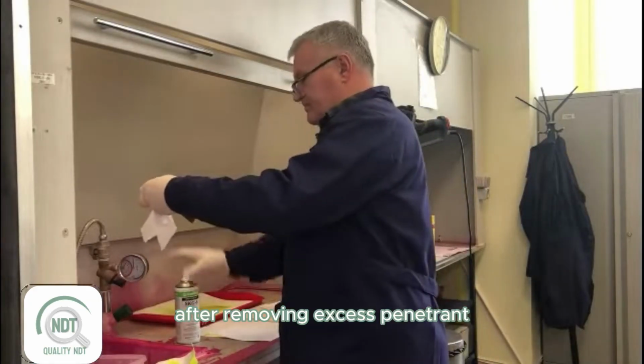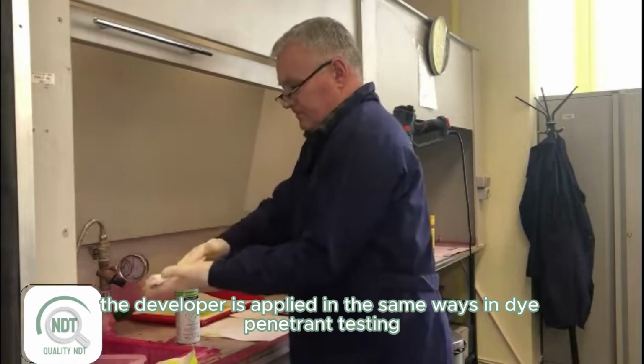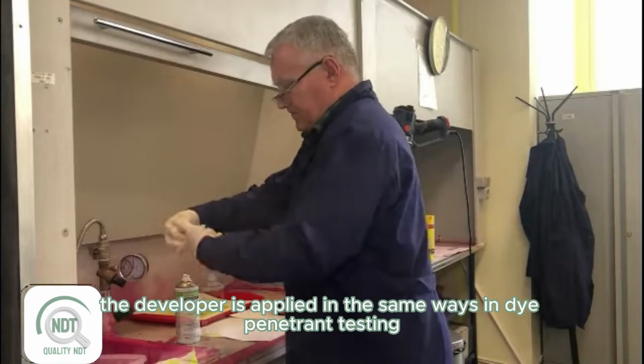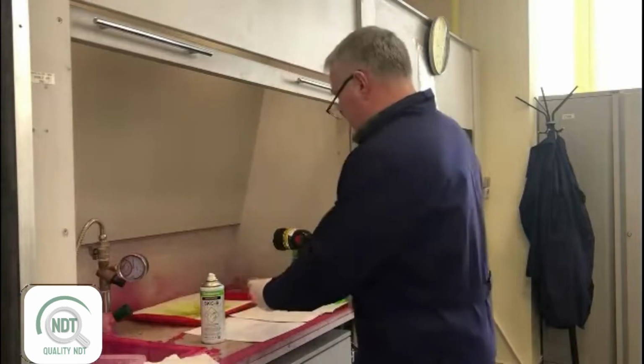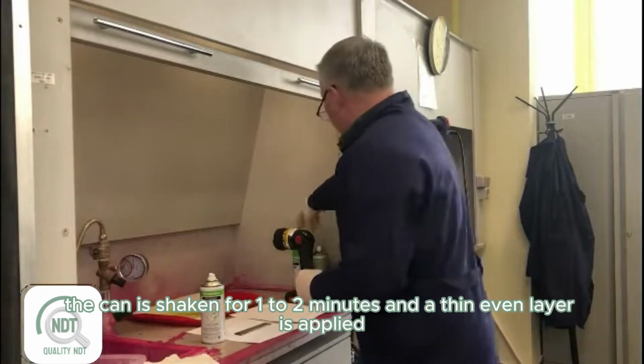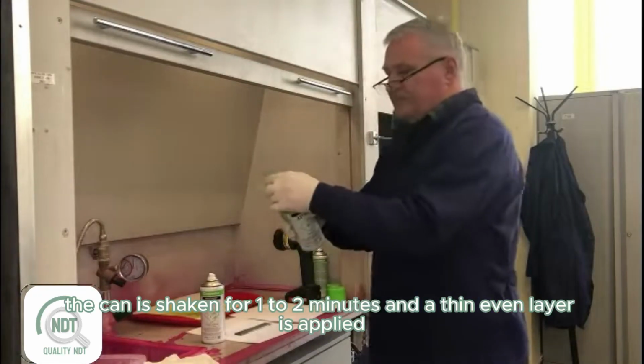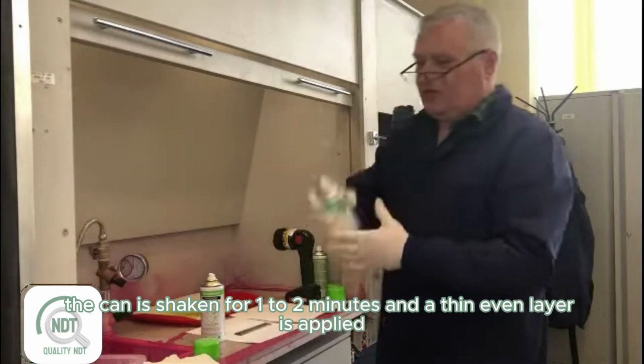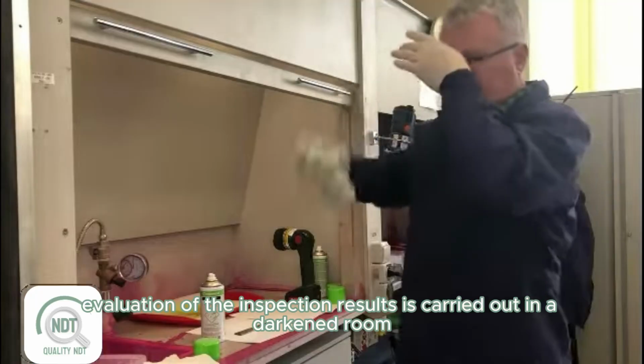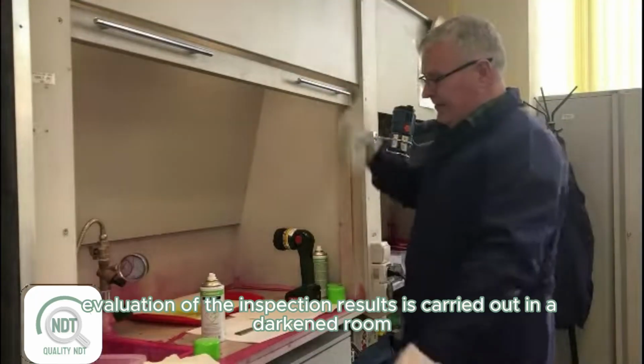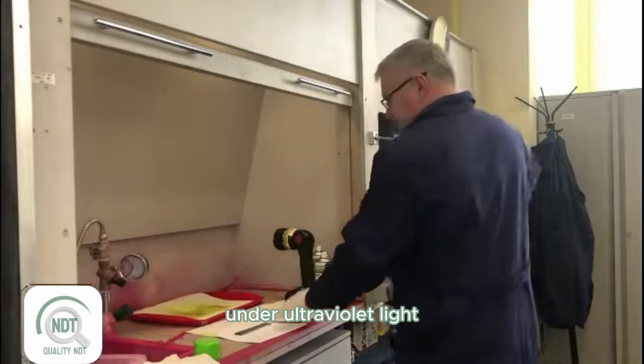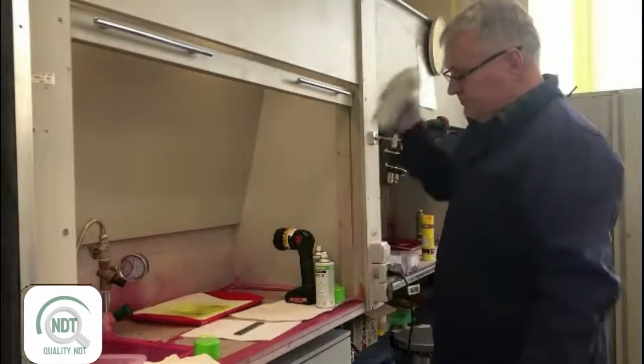After removing excess penetrant, the developer is applied in the same way as in dye penetrant testing. The can is shaken for 1 to 2 minutes, and a thin, even layer is applied. Evaluation of the inspection results is carried out in a darkened room under ultraviolet light.